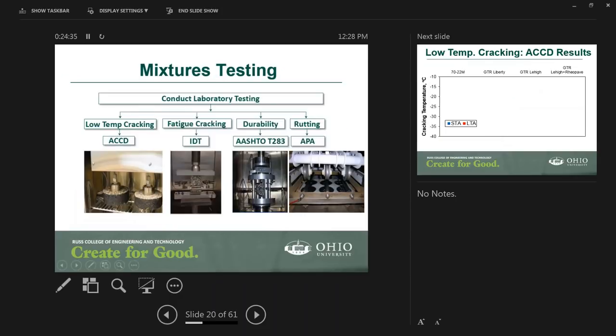So we did different tests for evaluating low temperature cracking, fatigue cracking, and durability, and what I mean by durability is mainly the resistance to moisture damage and rutting. For the low temperature cracking, we used the asphalt concrete cracking device, a device that was developed as part of an ODOT project by my colleague Sang-Soo Kim. We used the indirect tensile strength. It was a little bit of a modification because it was instrumented when we did the test. AASHTO T283, and for the rutting, we used the APA.